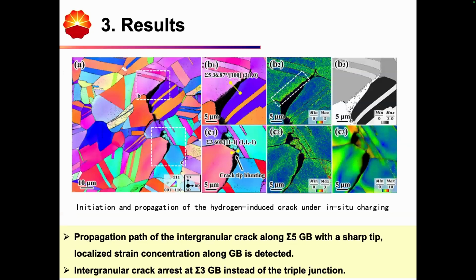This is about the observation of secondary cracks at the interface. We selected this region because both crack propagation and crack retarding are observed. For example, for the sigma 5 grain boundary, we can see it propagates, and some KAM maps show strain concentration along the propagation route.